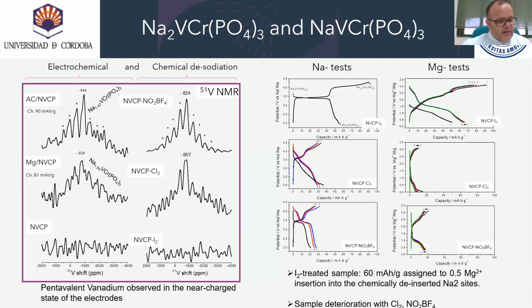The NVCP material charged up to 90 and 81 mAh per gram exhibits clear signals at 824 and 944 ppm, with their corresponding spinning side bands, respectively. These signals are located in the region ascribable to the existence of vanadium 5+, which is tentatively assigned to sodium 1.47 vanadium chromium 1 PO4 3 and sodium 1.55 vanadium 1 chromium 1 PO4 3.